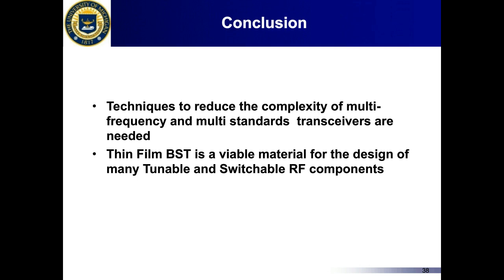How fast is the BST or BST-based device switching speed, and how does it relate to size? Inherently, the material can be switched on and off in picoseconds — it is very fast. The tunability of the material is maintained even up to terahertz. Of course, the speed of tuning is a function of the biasing circuit, so RC time constants in the biasing circuit can slow things down, but that is not inherent to the material. If the biasing circuit is designed correctly, it should be much faster than MEMS-based devices and comparable to diode varactors.